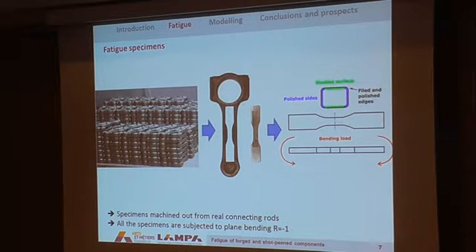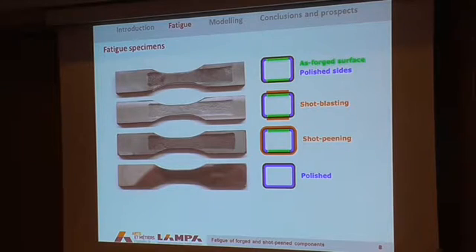And what we did, we used electric discharge machining to extract directly from the connecting rods some plain specimen. You see here the geometry of these specimens. And we apply plane bending purely reversed loading on this specimen. And we did that for different batches, different configurations, for as-forged surface before any mechanical surface treatment, for shot blasting treatment used to remove the scale from the surface, and for much more controlled shot peening, two types of shot peening, and we have a reference with no defect, no residual stresses, a polished batch.